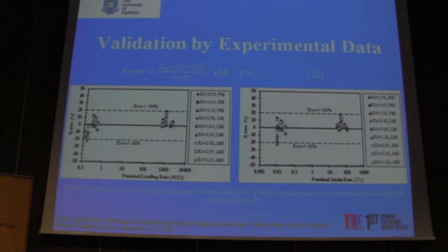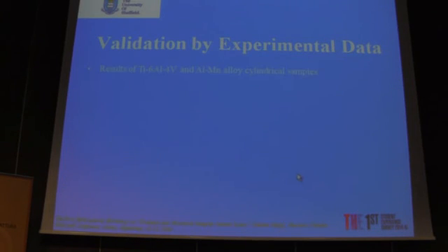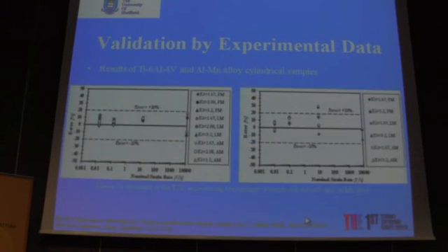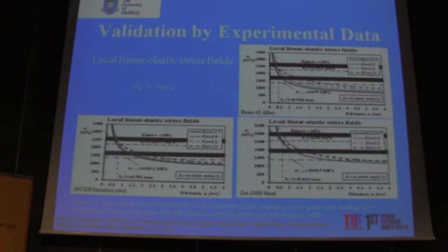All the errors fall within an error interval of minus and plus 20%. If we apply the same procedure used for the Al 6063-T5 to the other set of experimental tests, which is the titanium and another kind of aluminum alloy, we get the same accuracy, as the two figures show.